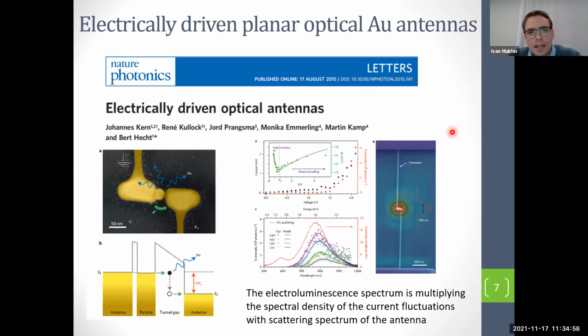Also, there are very nice experimental works showing that such a type of antenna can work perfectly. So this is an optical nano antenna, and here you can see small nanoparticles and a tunnel gap organized via this elegant shape of these particles. The thickness is about several nanometers, like shown here, and you can clearly see that such a structure can emit light visible by eye, or collected with this objective. And the group of Bert Hecht showed that if you change the applied voltage, you can increase the efficiency of light emission. Moreover, you can tune the wavelength of maximum emission.